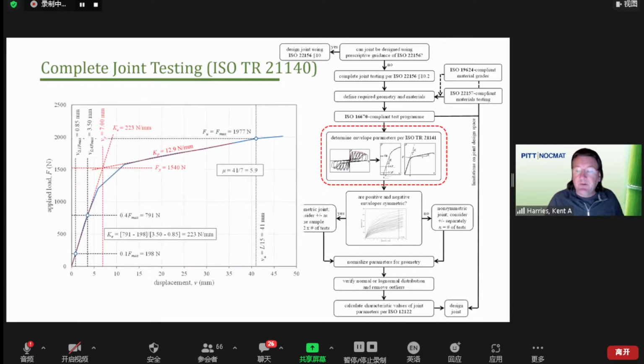And so just an example, so I showed the blue backbone curve previously. I'm plotting it in the positive quadrant here, but we have then all of the values that we need. We have the 40% of the maximum force, 10% in order to find K sub E, this red dotted line. We fit K sub P on, fits very nicely, nice bilinear behavior. Extend that back to find our yield point, and we have all of the data that we now need to move forward with. And so again, doing this to show the process, there is a data reduction process that has to be documented when we're doing this complete joint testing. And this is just simply one example.